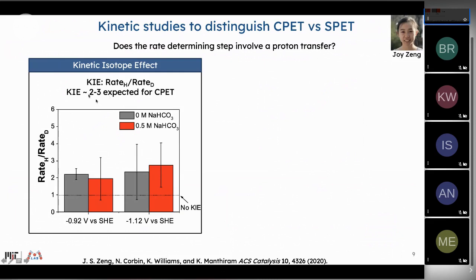First, we did a kinetic isotope effect study here at a lower potential and a higher potential, and you'll see in both cases that this is a KIE of around 2 to 3. This is reflective of the fact that there is a proton involved in the rate determining step in what we're showing here in particular.